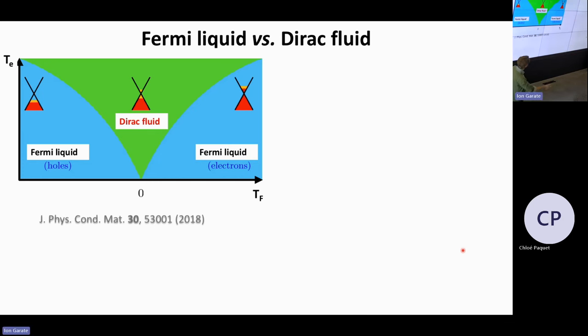Okay, last complication of this whole story is that within the hydrodynamic regime, you have two sub-regimes. So you have the Fermi liquid regime and the Dirac fluid regime. And the difference is how the Fermi energy or the Fermi temperature, it's just a Boltzmann scaling, relate to each other. So in the case where you have a relatively large Fermi temperature and a relatively small electron temperature, you're in a Fermi liquid regime. Then if you have a relatively large electron temperature but a small Fermi temperature, you're in a Dirac fluid regime.